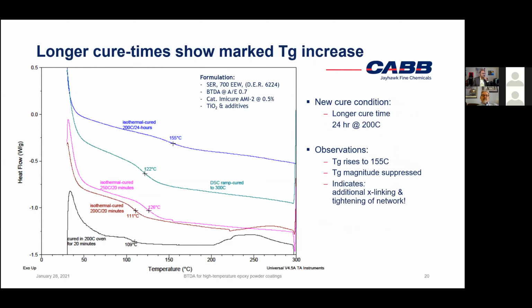We let it cure for 24 hours and then scanned it in the DSC. And this is what we get. A really nice bump, 155C. Now remember, the blue curve and the black curve, the only difference is that one is cured for 20 minutes and the other is cured for 24 hours.